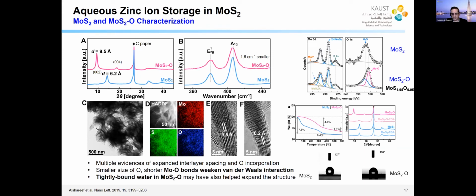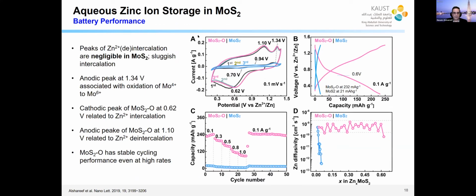Now we have the material, and then we want to make the battery. So this is a battery we made. The first thing you look at here, the A, is the CV curves. You see that the blue is the molysulfide. You hardly had any capacity because the interlayer spacing is small. The hydrated zinc cannot go in. But for the oxygen substituted molysulfide, you can see you have opened the CV curve, so there's substantially more capacity. The peaks in the discharge at 0.6 volt and the corresponding peak at 1 volt, up here, and here, these correspond to basically intercalation, the zinc going into the molysulfide and coming out. This peak here at 1.34 is due to the change in the moly oxidation state.